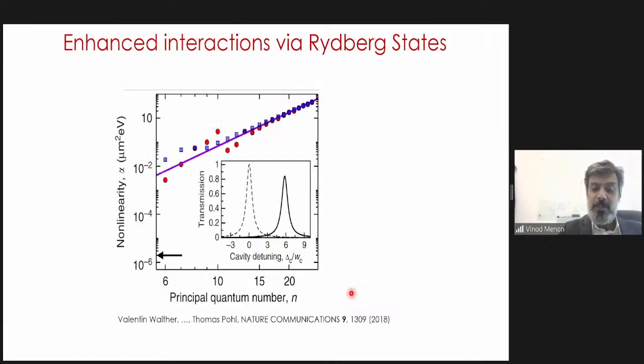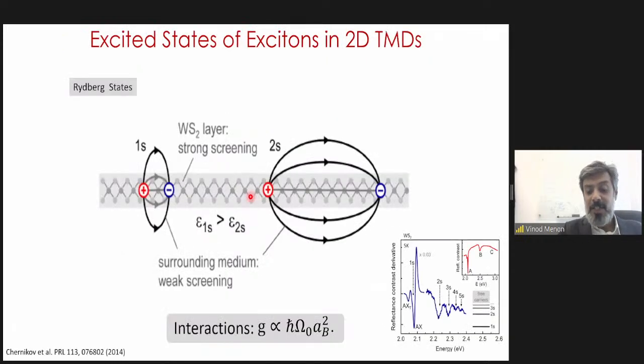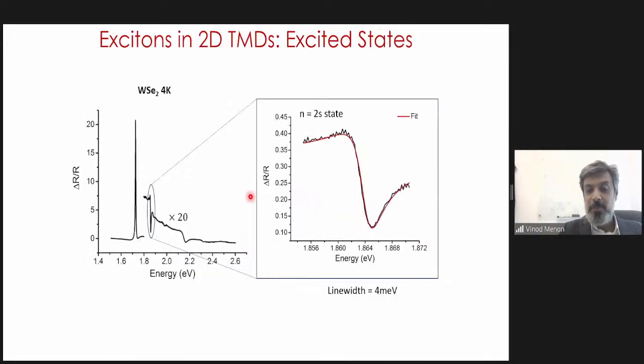So we were motivated by this theory paper which claimed that if I go to these large Rydberg states, then I can get increased nonlinearity. And so to prove this, we decided to look at the nonlinearity of the 2D material systems in the excited states. So our goal was very simple. We knew we could not do these higher excited states like n equal to 10 and so on. So the question we had asked was, can we see the scaling that one would expect by just going to the next excited state? So let's take 2s, let's take 1s, let's compare the Rydberg states and let's see what happens.